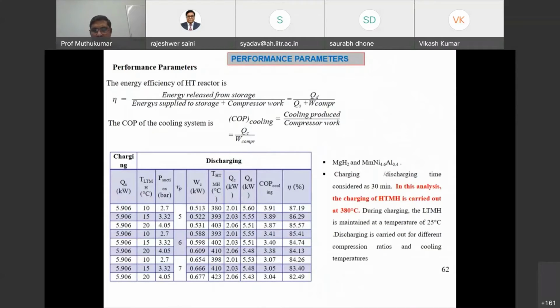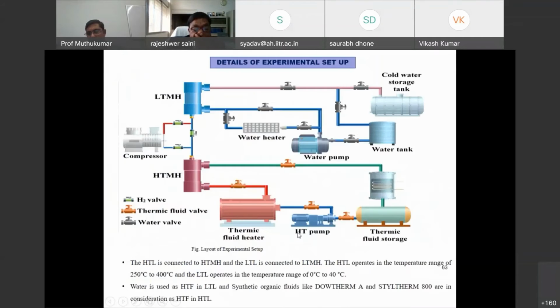Then we can have all the multiple outputs. So here you can see, the heat input is about 6 kilowatt. For 6 kilowatts of heat input, you can get a heat output close to about 5.6 kilowatt. In addition to that, you will also get a cooling effect of about 2 kilowatt. So here the overall COP will be close to about 0.4. The exergy efficiency or the energy storage efficiency is close to about 83 to 85%. Technically, no insulation is required here, and heat can be stored for a longer period of time.